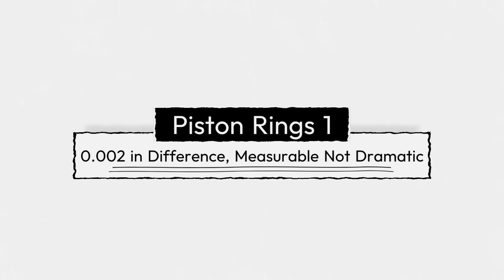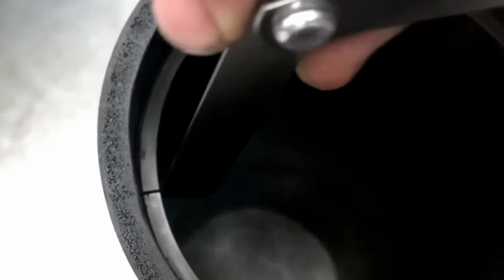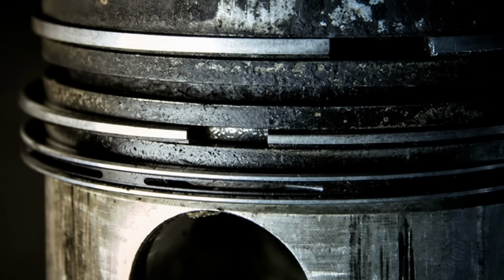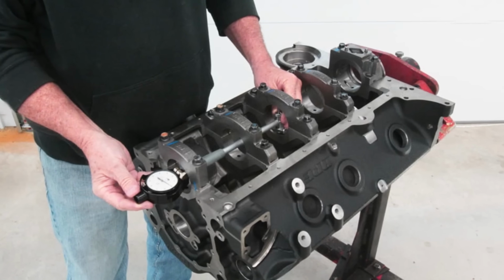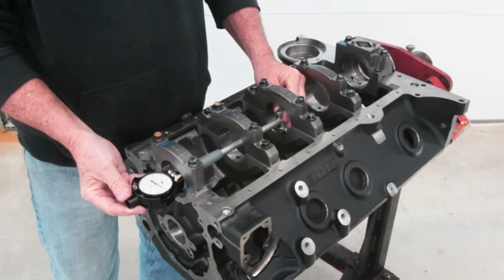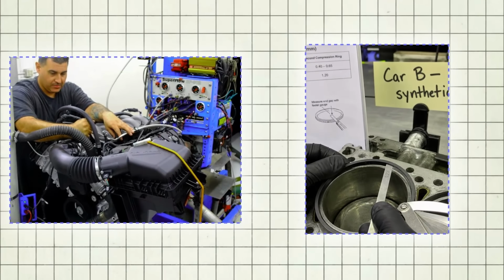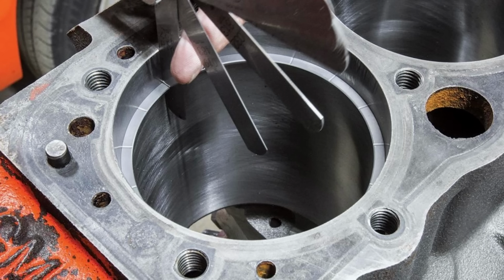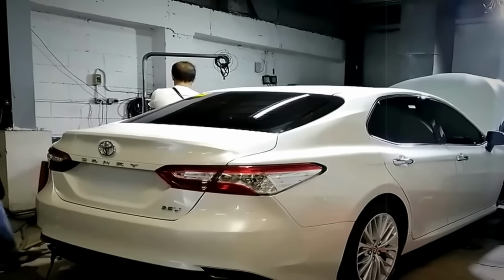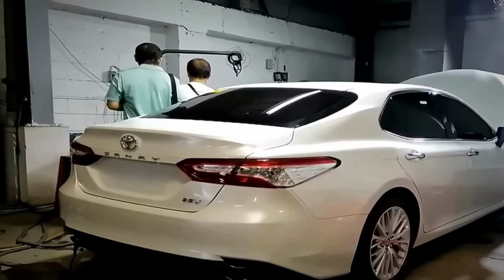Finding number 1, the piston rings told a different story than we expected. On Car A, the factory oil engine, the compression rings showed light but visible carbon glazing along the ring face, especially on cylinders 1 and 4, which tend to run slightly hotter due to their position in the block. The ring gap, measured with a feeler gauge against factory spec, had opened up marginally more than Car B, but we're talking about a difference of roughly 0.002 of an inch. Not catastrophic, not something that would show up as a performance issue at this mileage.